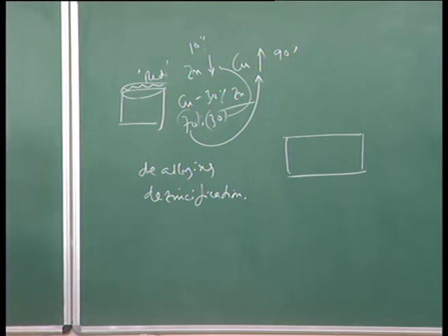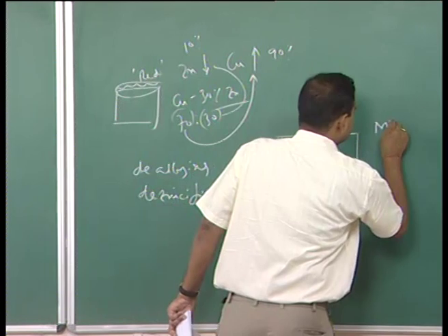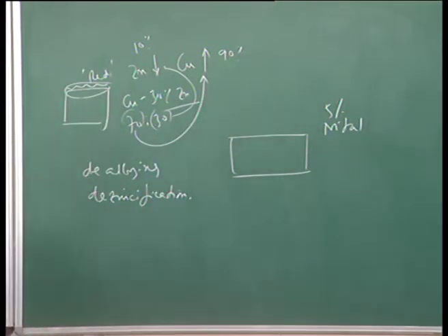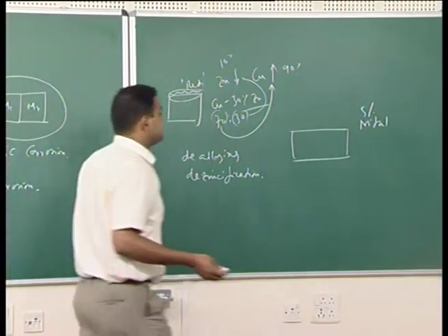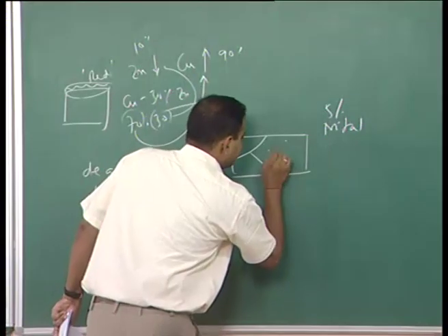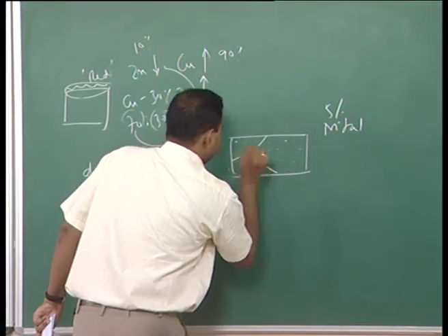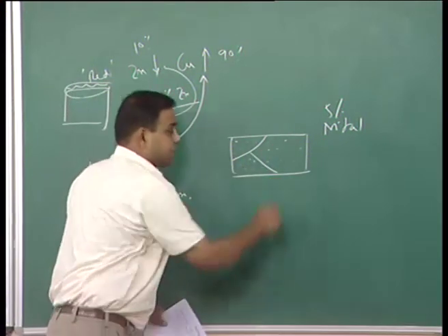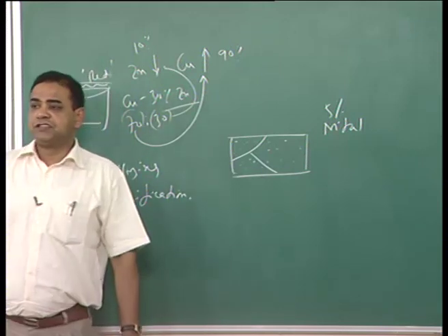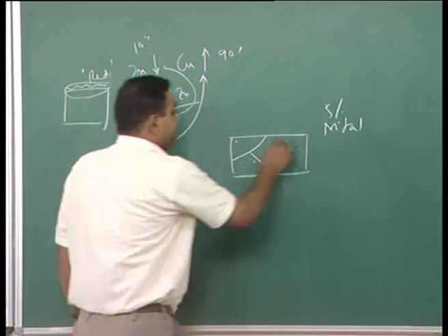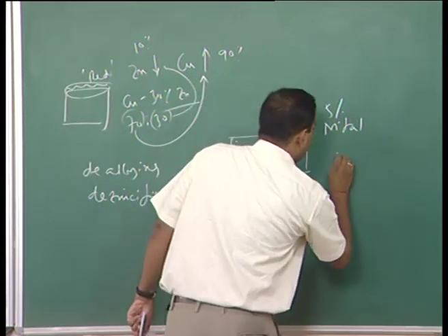If you etch it in nital solution, 5% nital, for a longer period, you will see that in addition to the grain boundary, there are some etch pits. There are some black regions on the grain. Those black regions are basically nothing but etch pits, and these etch pits are forming because of a sort of corrosion called pitting corrosion.